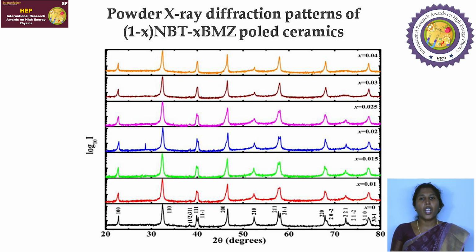The splitting of the 111 peak into 11-1 and the 211 peak into 21-1, and the appearance of the superstructure reflection 1/2(311), reveals that it possesses a rhombohedral structure with R3c space group. In all the ceramics, the splitting is seen, and it is confirmed that the synthesized pellets are possessing the rhombohedral R3c phase.